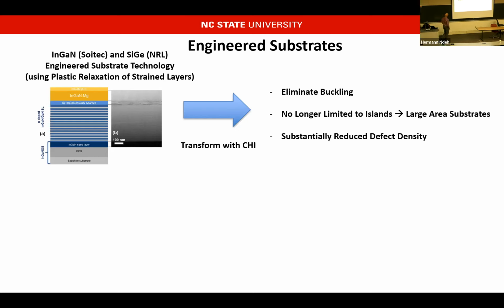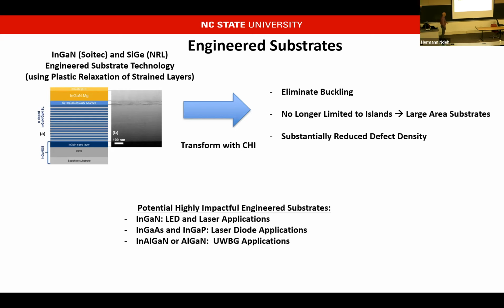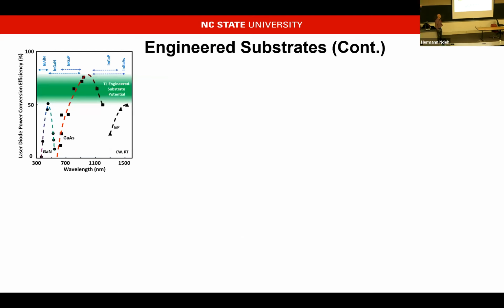But one of the problems here is that this work has generally been limited to small islands on material, because of buckling, because of the surface tension of the material. So when I go to relax it plastically, the material buckles. So we believe with the capability of the tool that we talked about, the CHI tool, that we can overcome this and do this in large areas. And if we can, it opens up, we think, all new kinds of opportunities to make ternary substrates and opens up the ability to use new alloys.